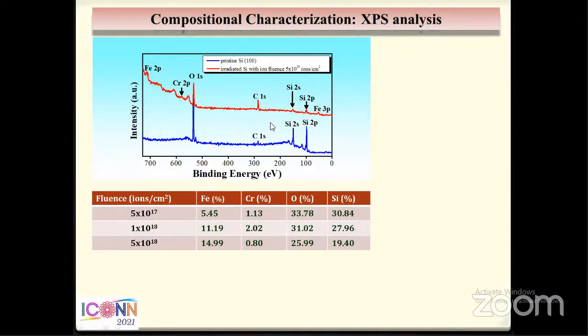Also, we have studied the compositional characterization by performing X-ray photoelectron spectroscopy analysis. Here also we observed that the blue line indicates a pristine silicon surface, and the red line indicates the silicon surface that is irradiated at the highest value of fluence. And here we observed that for the irradiated surface, apart from the other elements, the presence of iron and chromium can be clearly observed,